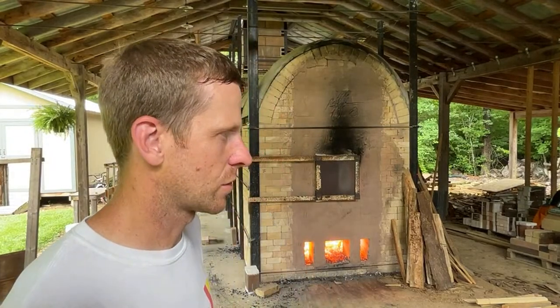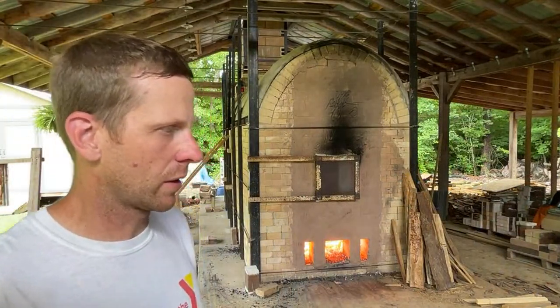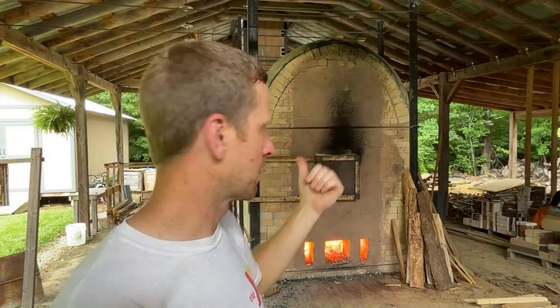All right, we are getting ready to do salting in the kiln in probably the next 15 minutes or so. I've got just a few minutes, so if anybody has any questions, I can answer those. Just to reiterate, we're about 2360 in the front and 2272 Fahrenheit in the back. I know the 10 and 11 are down in the bottom in the back, so I have cones top and bottom in the three different stacks. Cone 12 is already down in the top and bottom of the middle stack. We're just working on the back now, to get that cone down before we put the salt in. After we salt, we will be firing for a full hour.